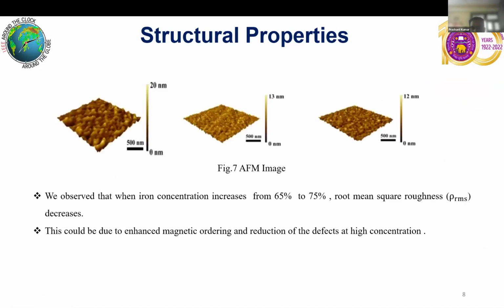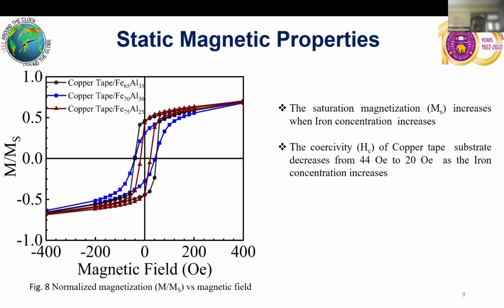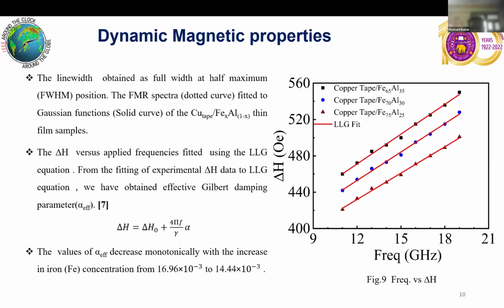This is the AFM image of the film which we have deposited. The AFM image and the values show that with increase in iron concentration, the roughness decreases. This basically shows the static characteristics, in which we find that the coercivity decreases with increase in iron concentration, and this is because of the enhancement in alignment of the magnetic domains of the deposited thin film.